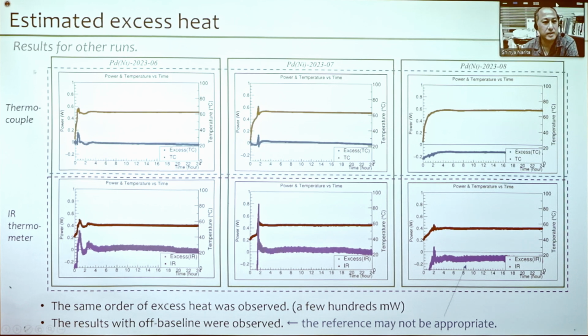Okay, so these are results for other runs, 3 runs. The top 3 plots are the estimated excess heat by the thermocouple measurement, and the bottom 3 are the excess heat by the IR thermometers. And now you can see the same order of excess heat, a few hundred milliwatts. And also we should note the result with off-baseline, in this experiment you can see the off-baseline there. So we suppose the reference may not be appropriate for this run.